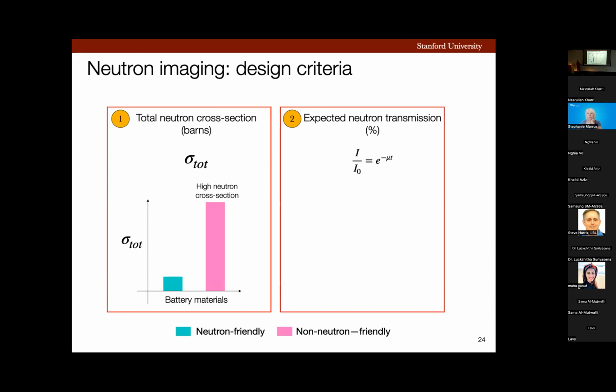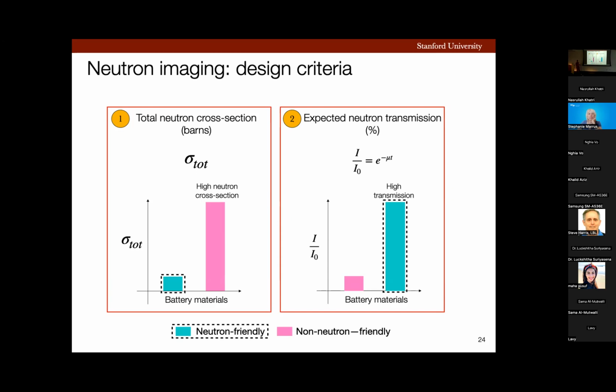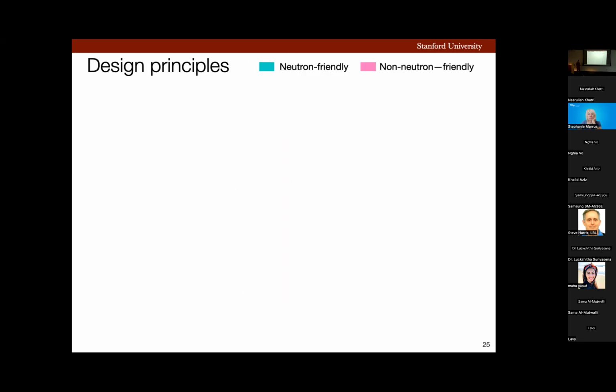Another important criterion is expected neutron transmission. This is Beer-Lambert's law, and here I over I naught is the expected neutron transmission, which, you would see, takes into account mu, the linear attenuation coefficient, which is related to sigma total. But it also takes into account the neutron path length through the sample. Thus, we have to replace the battery materials that offer low transmission with materials that offer high transmission so that we can distinguish lithium from the other battery components in situ in a full cell battery. Thus, to make a battery neutron friendly, we have to use materials that offer high neutron transmission and have low neutron cross-section. Now, keeping these design criteria in mind, I developed design principles.